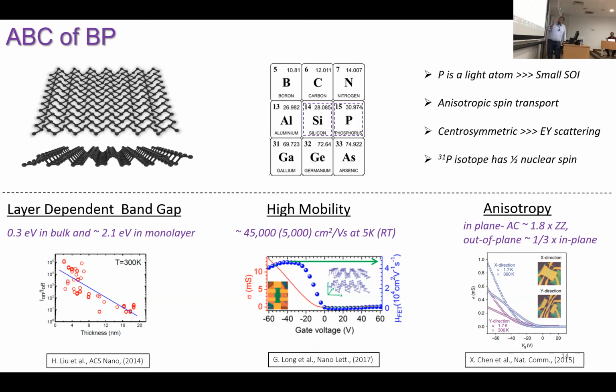And the material has a centrosymmetric structure, meaning that the Elliott-Yafet type spin scattering mechanism should be dominant. What it says is that if your electronic mobilities are high, your spin transport properties will also be high. So considering how high the mobility is, the spin properties should also be quite interesting. And the last one, which I'm not going to discuss today, is that it also has 1/2 nuclear spin, which would introduce more rich spin physics compared to other materials like graphene, etc.